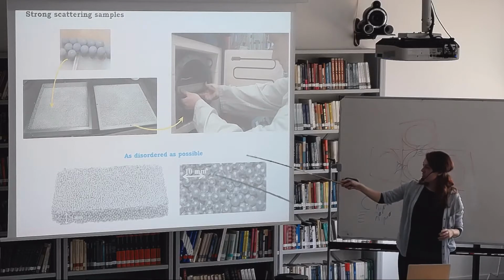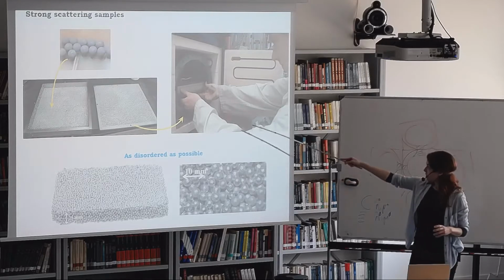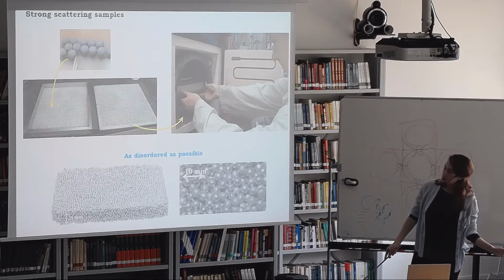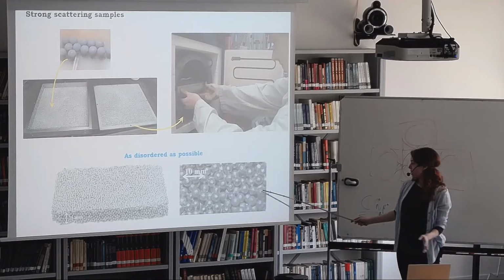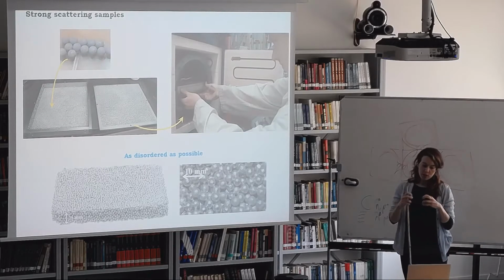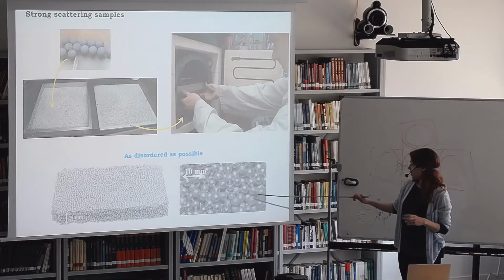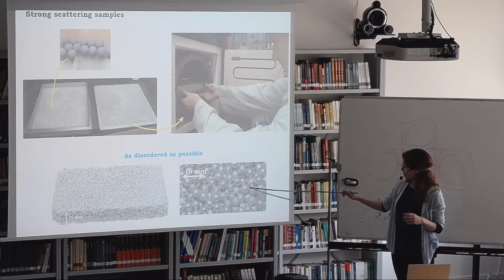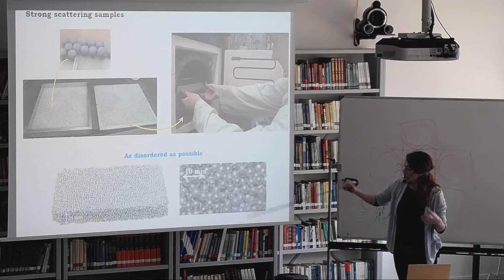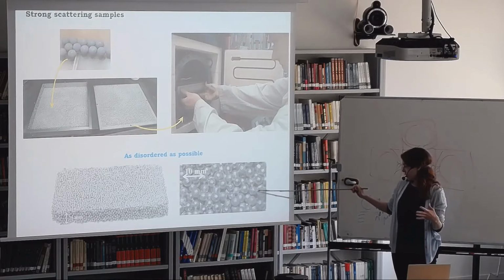OK, so we pour the beads into the mold. Then we put them into this oven, and we heat the oven to a specific temperature so that beads which are touching sort of flow together, and then they solidify with these solid necks between them. So we have this solid slab which retains the individual bead structure.